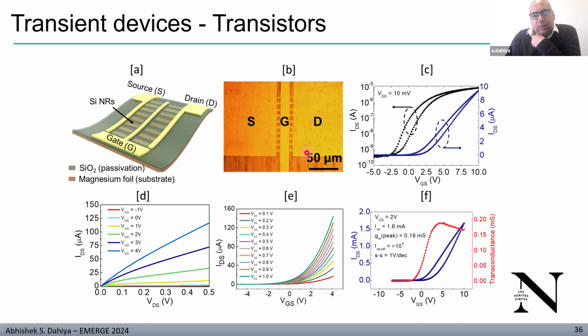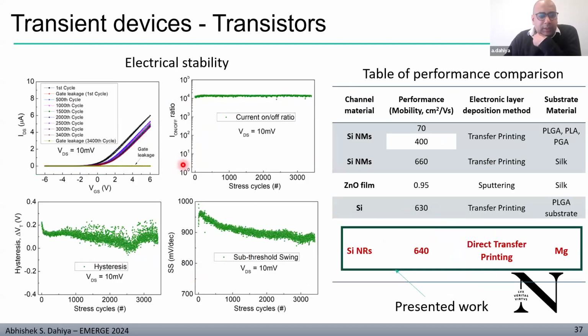This is typically how the device looks on the magnesium substrate. Transfer and output scans show nice ohmic contact and gate coupling, reaching a milliamp of current and transconductance in millisiemens, which is very impressive in terms of the state of the art. So this is the table which compares other devices fabricated on biodegradable substrates. People have explored PLGA and silks, and in our case, we have done it on magnesium.